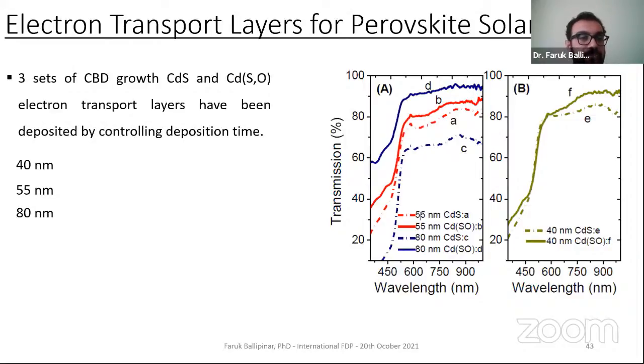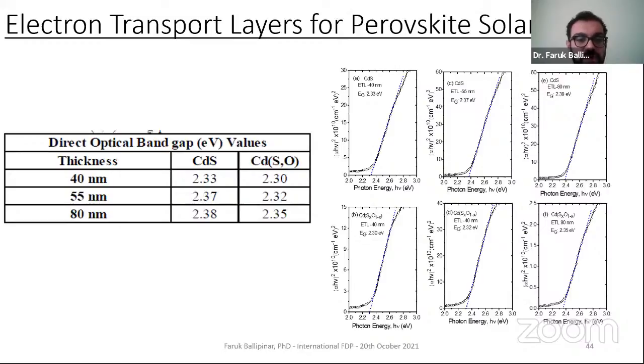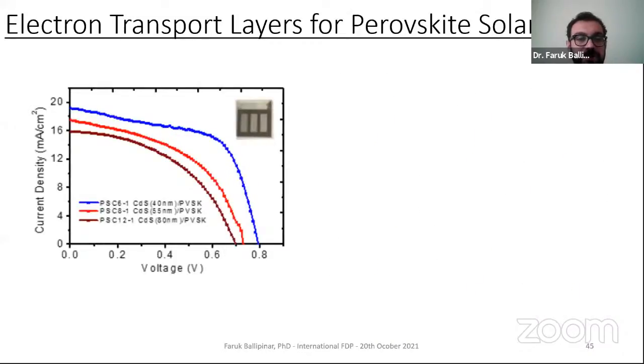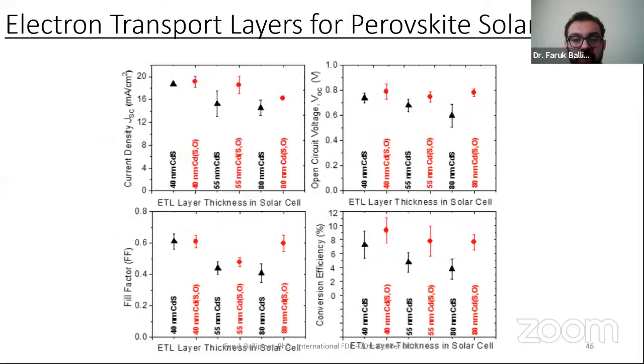Three sets of different electron transport layer thicknesses for perovskite: 40 nanometer, 55 nanometer, and 80 nanometer, for cadmium sulfide based perovskite and cadmium oxysulfide based perovskite. Again, band gap calculation from these two sets. So this chart is for all thicknesses, the black ones are the cadmium sulfide based perovskite material, and the red ones are cadmium oxysulfide based perovskite material.